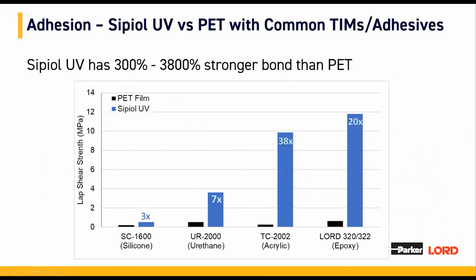Silicones, urethanes, acrylics, and epoxies are some of the most common thermal interface materials or adhesives used in battery assemblies. These materials were chosen from the Parker Lord portfolio to compare the different chemistries for adhesion strength. As shown in the graph, the substrates which were coated with Sipiol UV, indicated by the blue bars, achieved 300 to 3800% stronger bonds than those substrates that were wrapped in PET film. Strong adhesion is critical in battery applications where delamination or debonding of TIMs can lead to thermal runaway and safety issues.